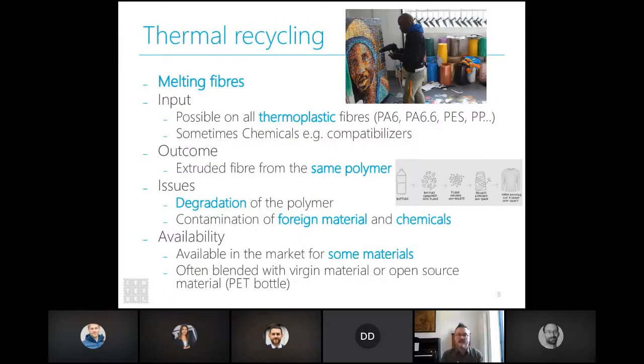The next recycling technology is actually melting down plastics, like the artist you see in the picture. All thermoplastic fibers you can melt down and spin again into a fiber. Sometimes you need chemicals to improve the end result, like compatibilizers. Those are used when you have a contamination of another thermoplastic material that doesn't blend in well. They make sure that those two materials stick together and you have a better quality. The outcome is a fiber from the same polymer. So you will limit the material change with this technique.